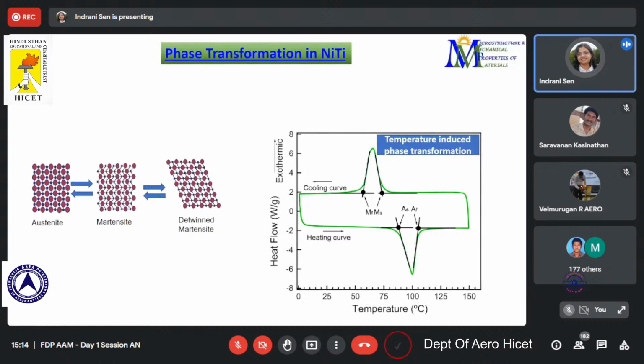Now all this has been done without the application of temperature, keeping the temperature constant, an isothermal condition. Now there can be another situation when we are not making any change to the stress level, but the temperature is being changed. Initially the alloy at higher temperature is austenite, and when we cool this, there is a phase transformation happening. It starts at the martensite start temperature, finish temperature, etc. This is the differential scanning calorimetry curve, again an experimental curve, and you can see that as we heat the specimen back, at a certain point the martensite is converted to austenite once again. There is a start and finish temperature, and once it reaches the higher temperature, it is back to the austenite phase.